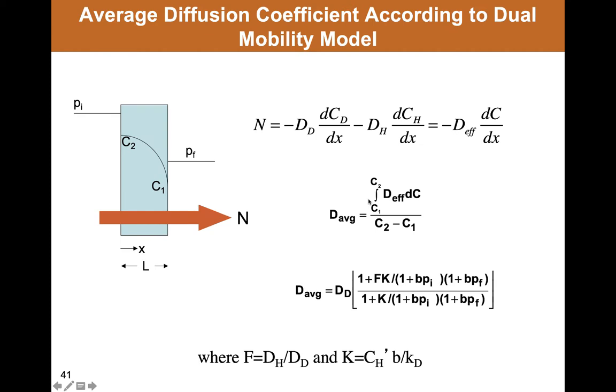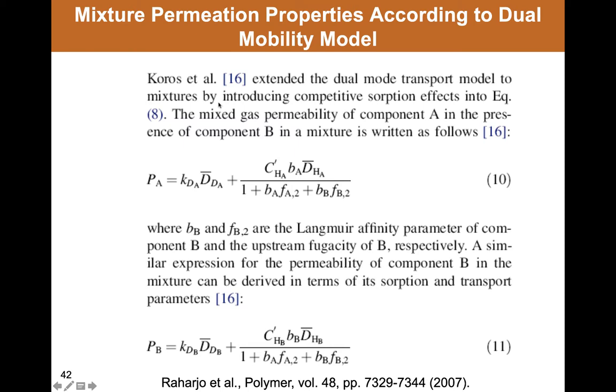One can average diffusion coefficients in this particular model, and the way that the average diffusion coefficient is calculated for this or any model is shown here. I won't belabor this point for the time being, except to show you some indication of how this model has been expanded or extended to predict permeability in mixtures and what these mixture effects can be.